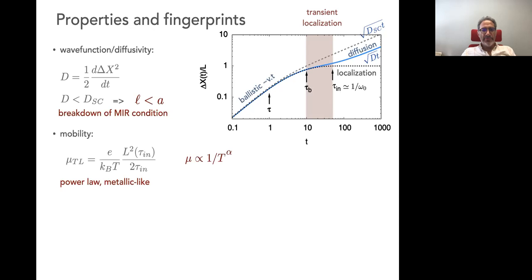Now, the second consequence is that the mobility, I'll come back to this formula later, but just take it now here. There is this prefactor that comes from Einstein's relation. And so you already have a factor of temperature here. And also the localization length here depends on temperature because the amount of disorder depends on the temperature. So you end up having a mobility that scales like a power law. So you have a power law, yet it is not band-like.